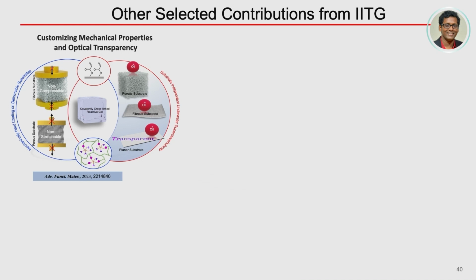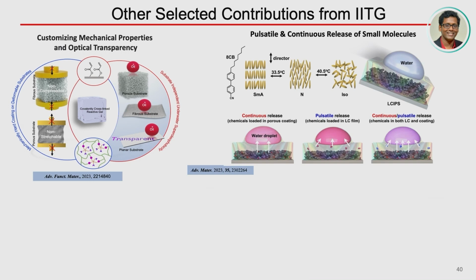Just to give you another glimpse of what we are doing further in our laboratory, we're also playing with this underwater super oleophobic coating, which is not only playing with the adhesion and the extreme repellence, it also plays with the mechanical property. You can make the material extremely hard when you are depositing on highly deformable substrates. Again, Angana was one of the lead contributors in this work.